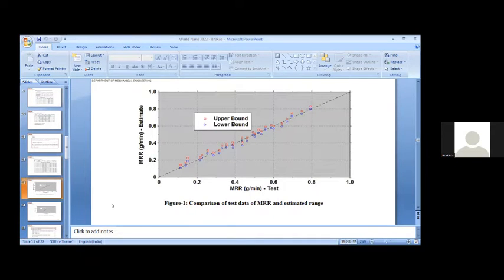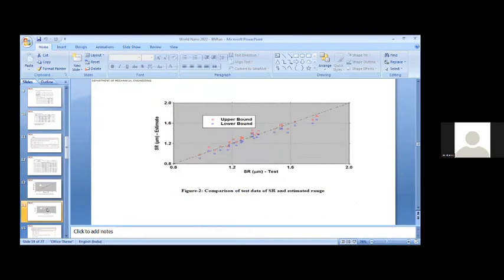Now, for the 27 data points, when you see the material removal rate test and estimate, with the lower bound and upper bound, the exact 45-degree line is passing through the middle of them. Only a few are very close to the test data. Similarly, for surface roughness, we have estimated the lower bound and upper bound, and the test data falls between them. Only a few data points are close to the bounds. This clearly confirms that there is no necessity to go for a complete full factorial design of experiment. We will do a few experiments as suggested by the Taguchi design of experiment, and we can get the complete information.